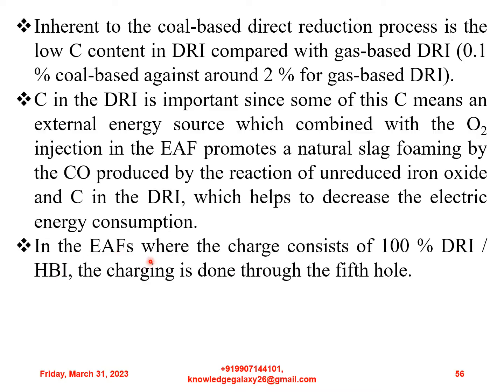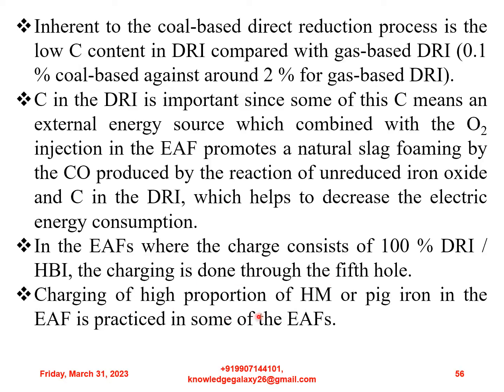In the electric arc furnaces where the charge consists of 100% DRI or HBI, the charging is done through the fifth hole. Charging of a high proportion of hot metal or pig iron in the electric arc furnace is practiced in some of the electric arc furnaces.